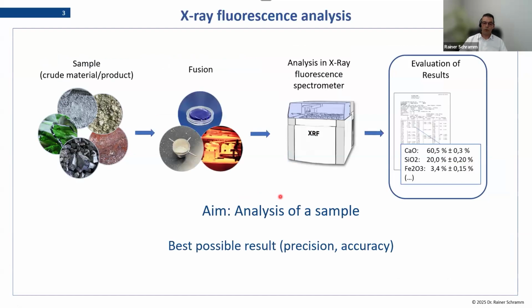Generally, if we do XRF, we have, of course, our sample, and to measure it in the XRF instrument, we need to prepare it. And in the end, we get our result. So this is the classical workflow. And sample preparation in XRF means mainly weighing the sample and weighing the additives. Like, for example, in fusion, we have to add a flux to dissolve the sample into it, or sometimes, if we have, for example, slags or ferroalloys, we also have to add some more additives like oxidizers, and also there we need to weigh them.